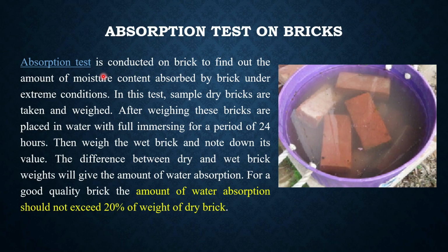We already know absorption is how much amount of water a brick is going to withhold inside it. Okay, so how are we going to test it? We take a dry sample of brick, weigh it, and note the value, and then you have to soak the brick for 24 hours in water. After that you take the brick, wipe off the remaining water on the surface of your brick, and then you weigh it again.